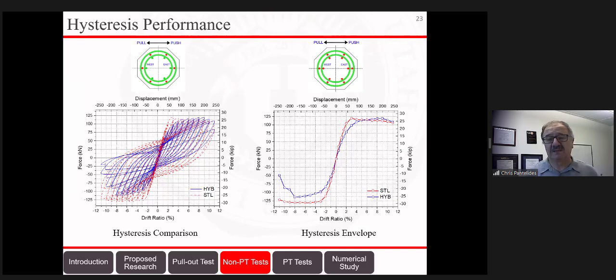So there is less than 10% difference in capacity. The ductility of the steel column was a little bit higher, 5.5, and the ductility of the hybrid was only 4. But even 4 is a good ductility. And on the right-hand side, you can see the hysteresis envelope, which explains what I just said.